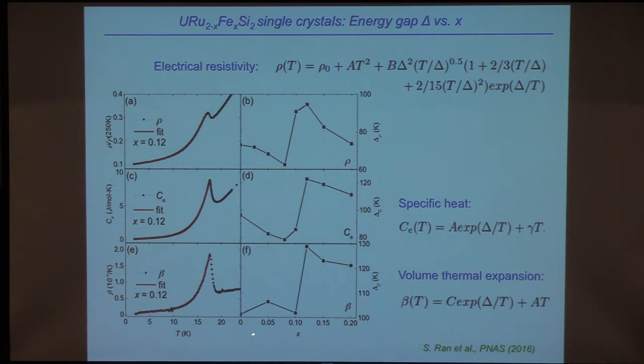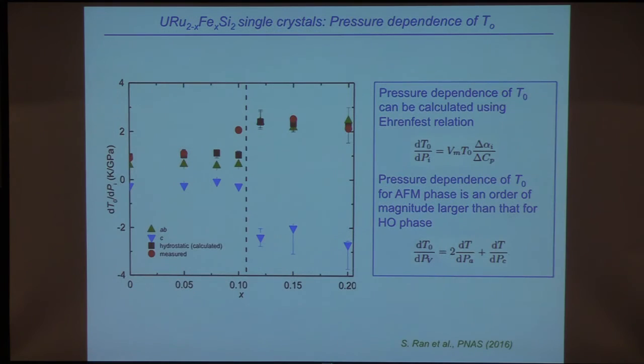So this is energy gap versus X. And you can see that as you go through the transition, the energy gap decreases, and then it jumps up and decreases. So there's an energy gap in both the hidden order and the large moment antiferromagnetic phase, and you can see that it behaves similarly as deduced from these three different measurements. And this shows the pressure dependence of the hidden order and the large moment and the Néel temperatures. So this is the hidden order phase right here.